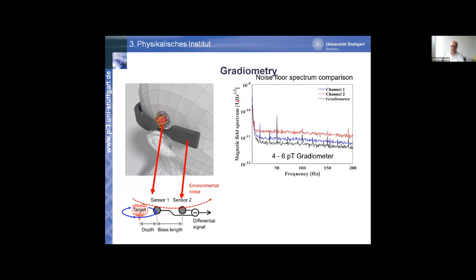So I plot magnetic field spectrum in Tesla per square root of hertz, going from nanotesla to picotesla. We operate these gradiometers, and what I plot here is actually the sensitivity curve of this gradiometer as a function of frequency of the magnetic field you want to measure, for the two channels we were employing. So this is the blue channel, one channel, and this is the second channel. And so the overall gradiometer, which subtracts the two channels, achieves a sensitivity of a few picotesla per square root of hertz. And now we are trying to push this towards, say, the 200 femtotesla level sensitivity.